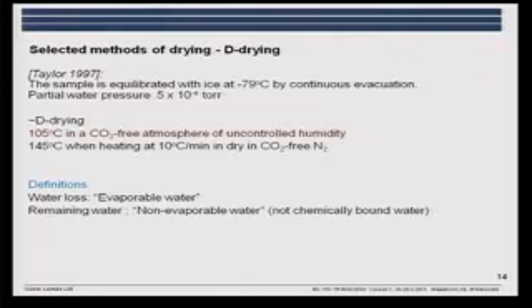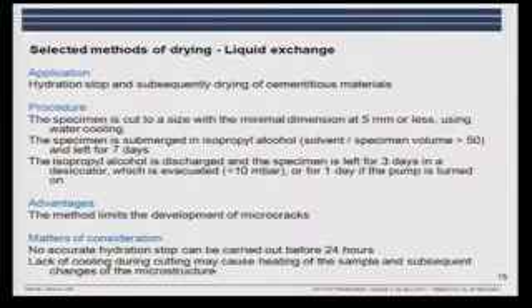And again here, we're talking about the water loss. It's defined as the evaporable water, and the remaining water is the non-evaporable water. And as you first saw before, it's not identical to the chemically bound water. And I'll just mention a method which has been used increasingly, in connection with the recent Mercury project and also with the core projects, where we have liquid exchange. And here it's liquid exchange with isopropanol or isopropyl alcohol.